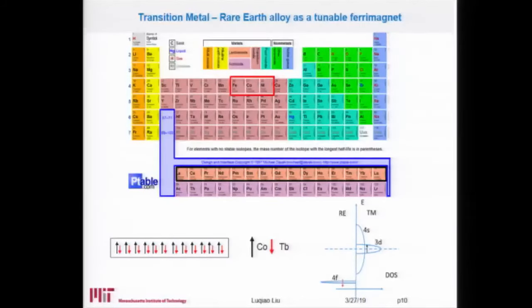So people already know that if you make an alloy out of those two different types of elements, they will naturally be aligned antiparallel with each other in terms of their spin due to the exchange interaction between D electrons in cobalt and F electrons inside terbium. At the same time, because rare earth elements' magnetism mostly comes from 4F electrons, but their 4F electrons are also very far away from the Fermi surface, a few electron volts below or above the Fermi surface, that means across the Fermi surface, only the transition metal here, the cobalt, dominates the density of states. So if you measure it electrically through the transport property, it mostly reflects the cobalt spin orientation.